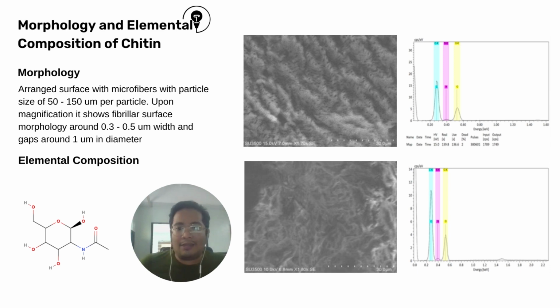For morphology and elemental composition of the chitin, an arranged surface of microfibers with a particle size of 50 to 150 micrometers per particle was observed, and upon magnification, it shows fibrillar structure morphology of around 0.3 to 0.5 micrometer with gaps 1 micrometer in diameter. As expected from the EDS results, carbon, nitrogen, and oxygen were detected in all extracted chitin.